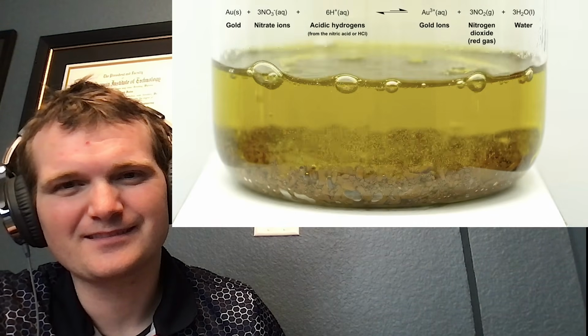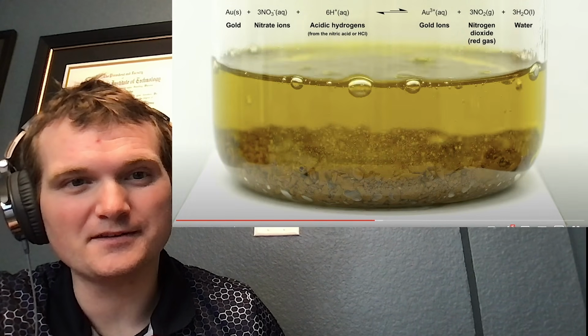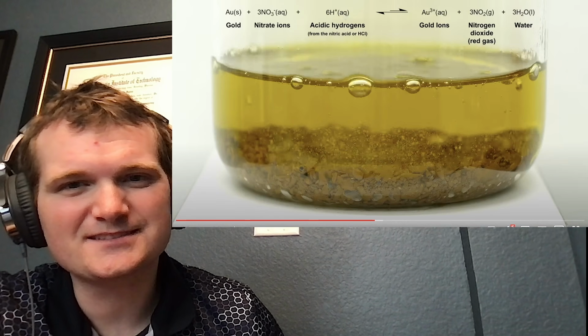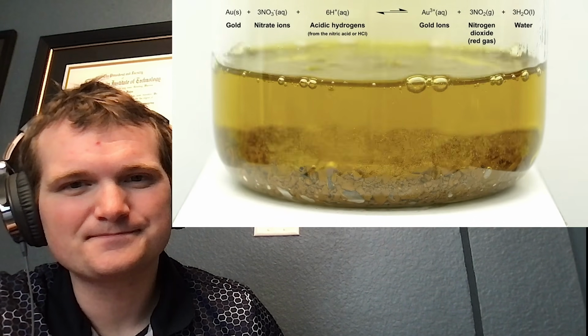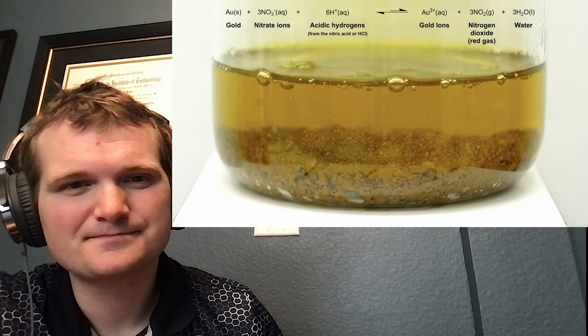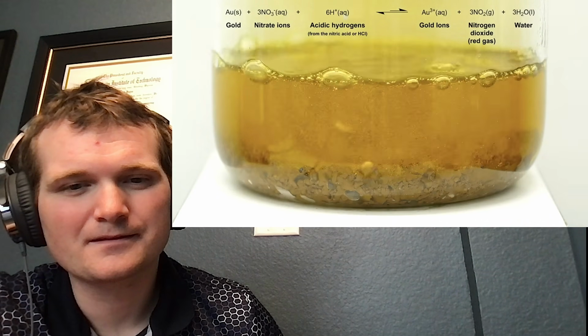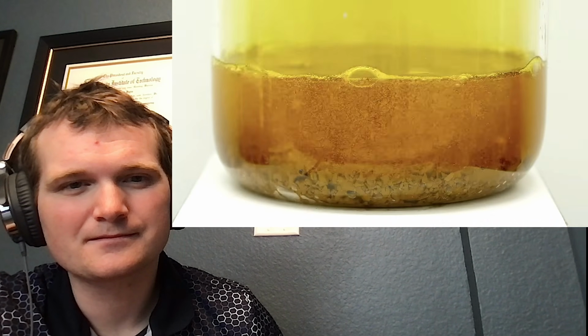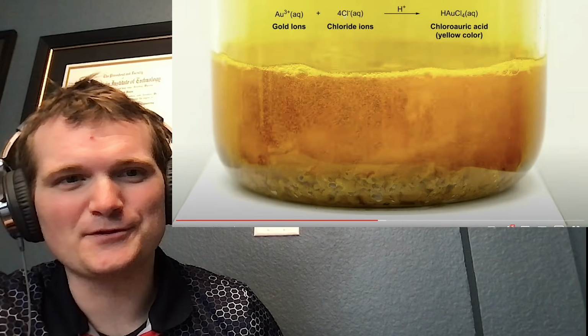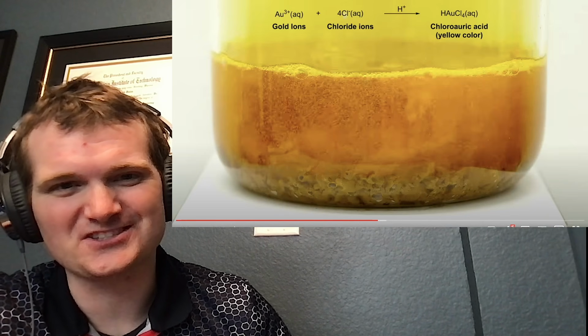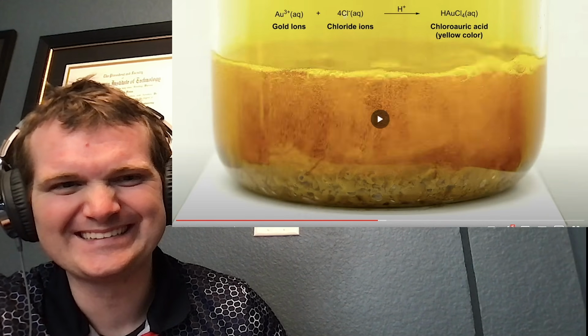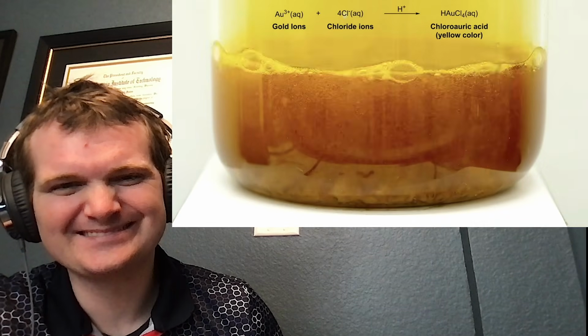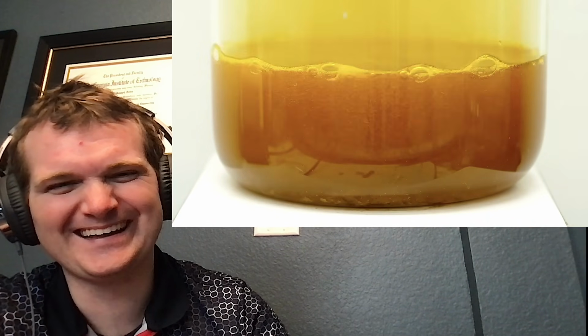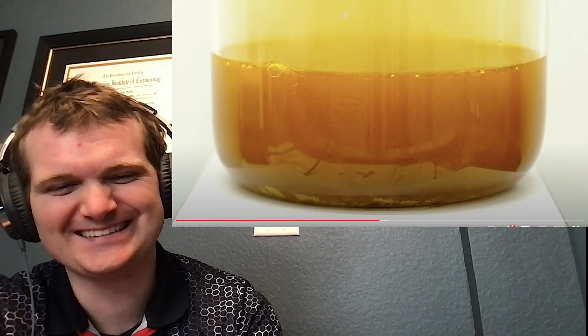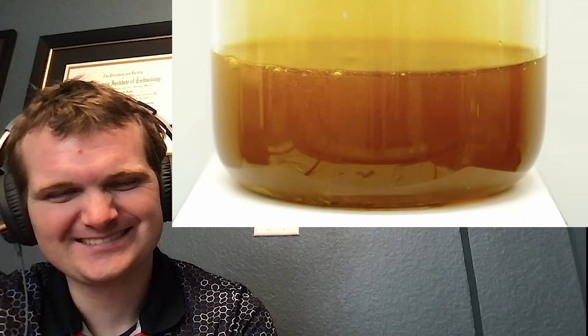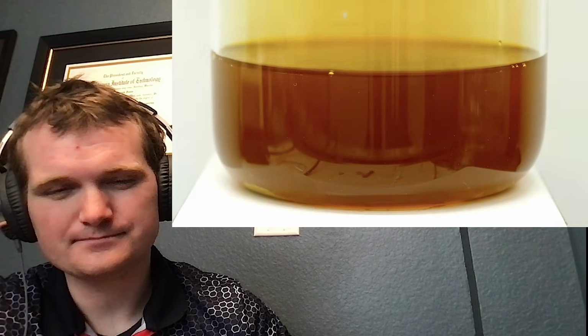They work together, where the nitric acid starts by oxidizing an extremely small amount of the gold to make gold 3+ ions. This reaction is really unfavorable though, and almost immediately after they're made, they revert back to being metallic gold. With the hydrochloric acid present though, it can attack the gold 3+ ions and convert them to chloroauric acid. This breaks the equilibrium between the gold and the nitric acid, and the gold ions are continually fed forward to make the chloroauric acid.